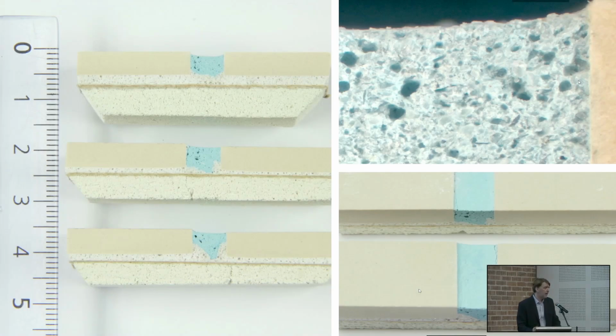Unfortunately, this is not working, because we analyzed many times in our lab the conjunction, the touch point between the grout and the tile, and any grout, even the epoxy grout, in the edge between the tile and the grout, there can be some little voids. So you cannot guarantee that the water is not passing through. So let's get this point out of the way. On the floor, outdoor I mean, the water will always enter in the joint, no matter what you do. You can reduce it, but the water will enter in the joint. And this is not a problem, it's normal. Because there are other ways to stop this kind of penetration, but not the joint, okay?